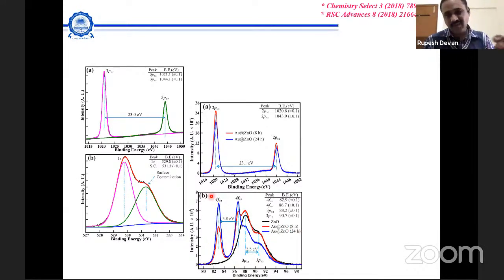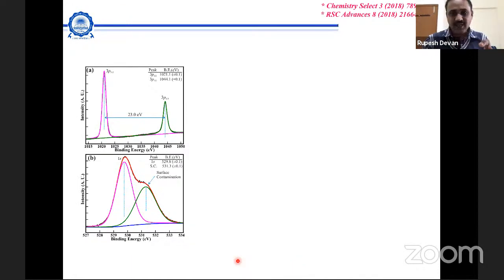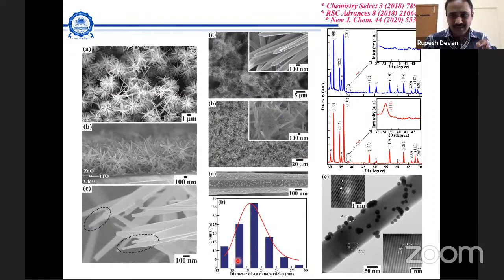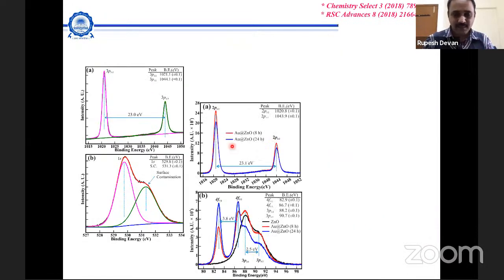Now the question is, even though these particles are approximately 20 to 30 nanometer, and XPS says that the signal comes out only from 10 nanometer, then how come we are getting signal from zinc? We have to remember that these particles are being coated on the surface, and they are not continuous. You can see over here, these are just randomly aligned. So for XPS, both the signals are accessible. That's why we could get this information out.